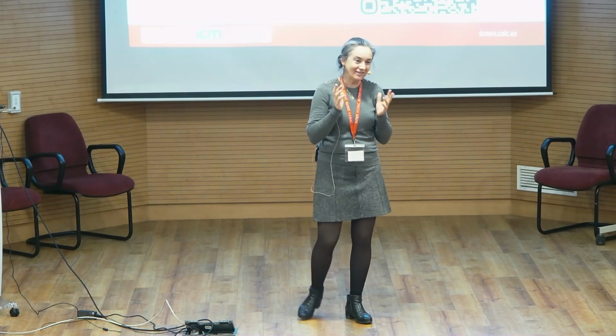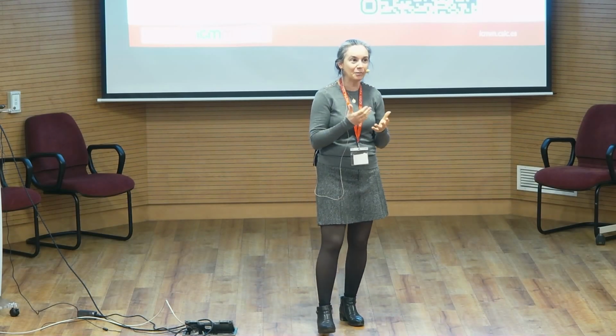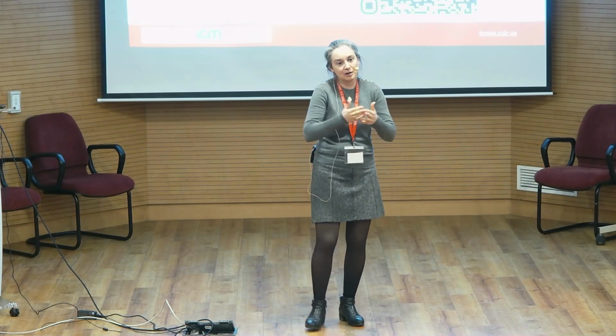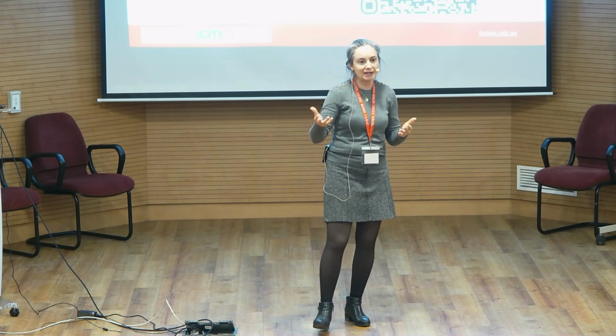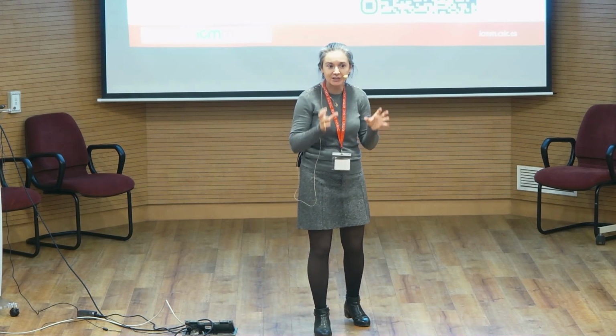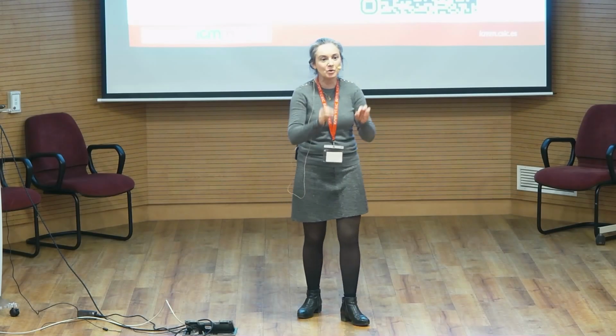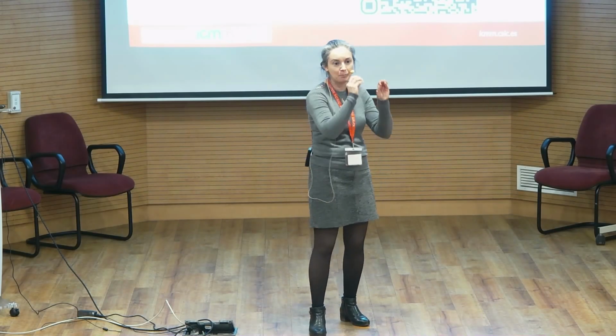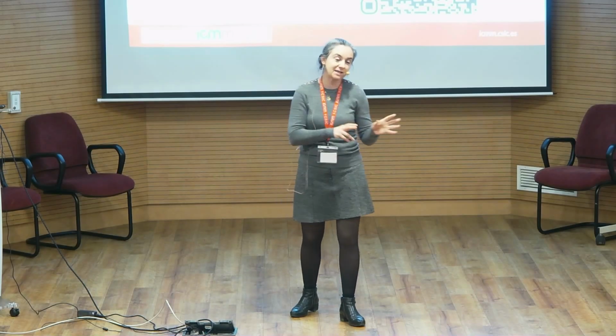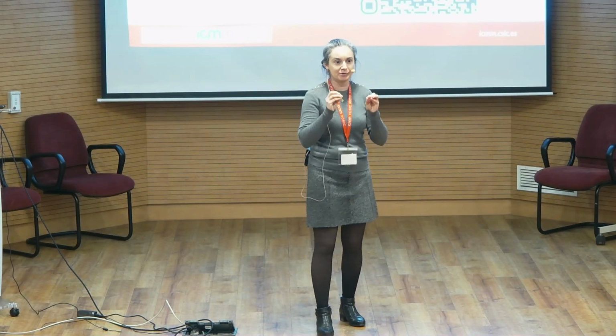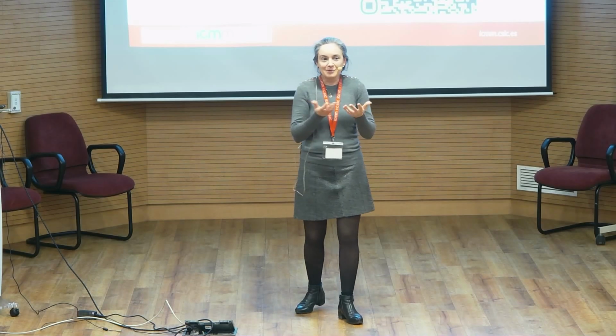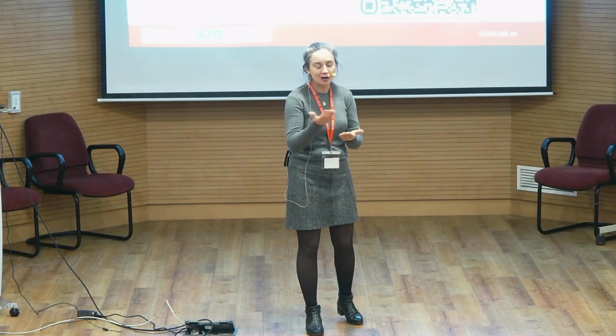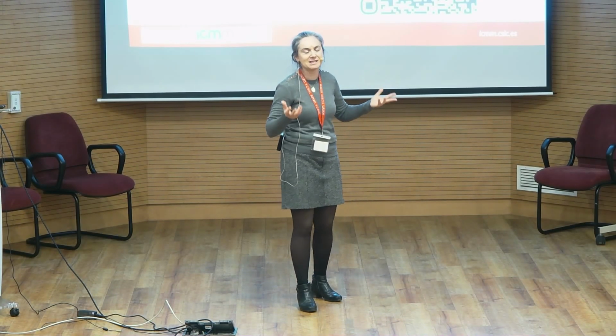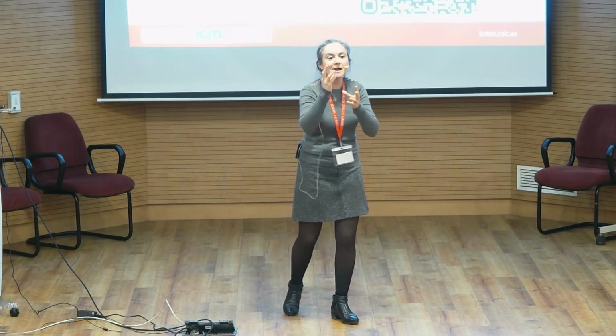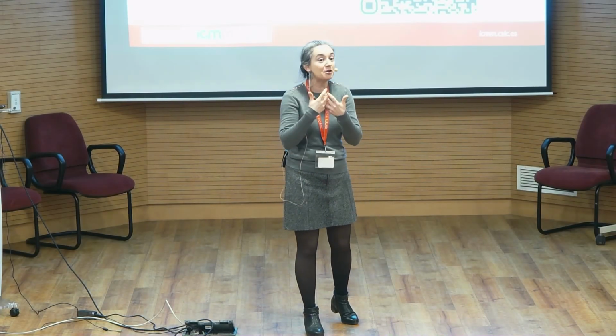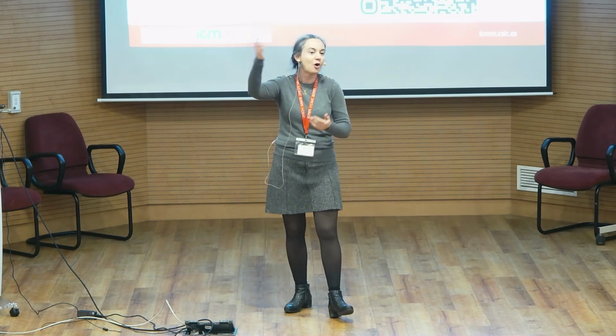So what we really believe and are pushing to prove is that it's just a matter of the longer time that you need to record, and you will finally find neurons responding in all the cases, because all the scaffolds are exactly the same, characterized with the same properties, fabricated in the same batch, implanted in sister, in this case brothers, because they are male rats, brother rats. So there are no other differences. You do the histology and they look, as you have seen there, basically the same. There's a little bit more diameter of blood vessels, but it's only a little bit. That cannot explain why you have neurons responding in the brain or not.